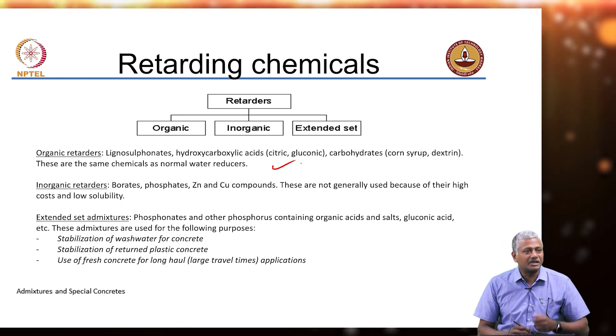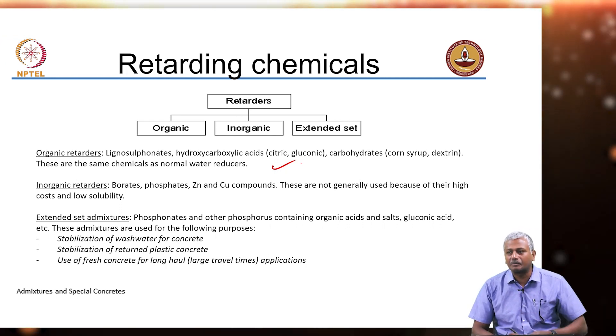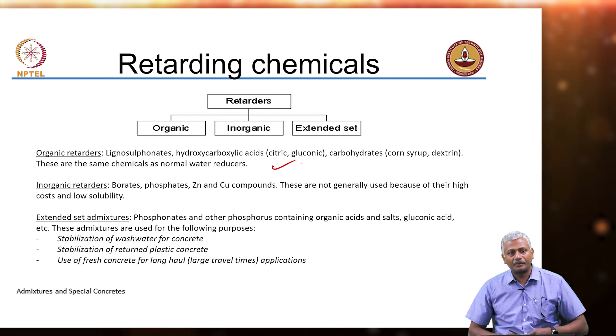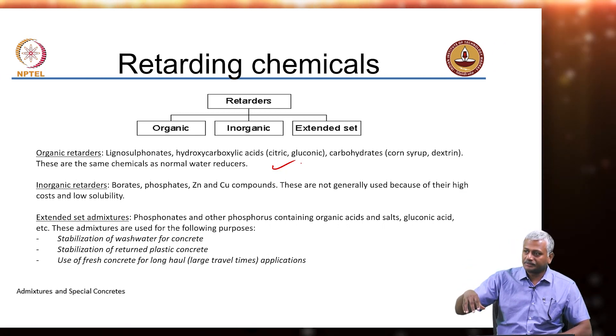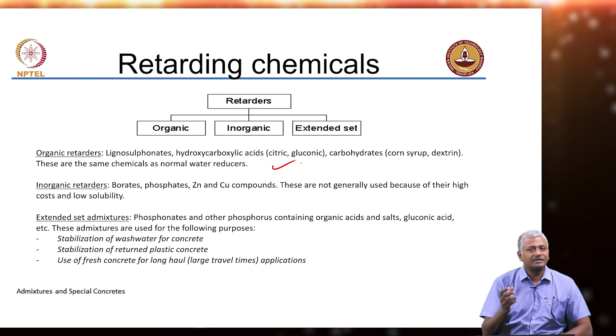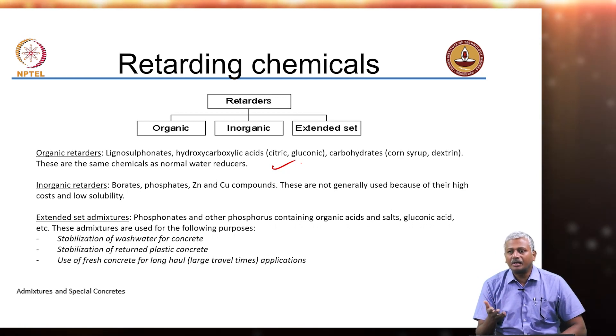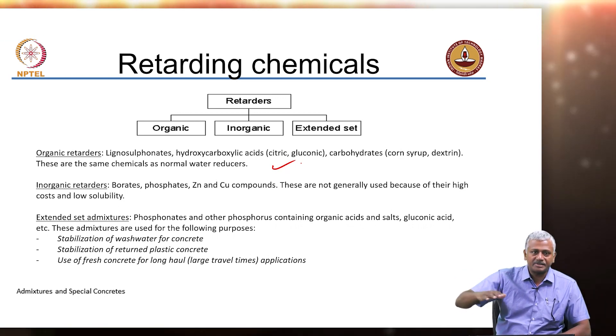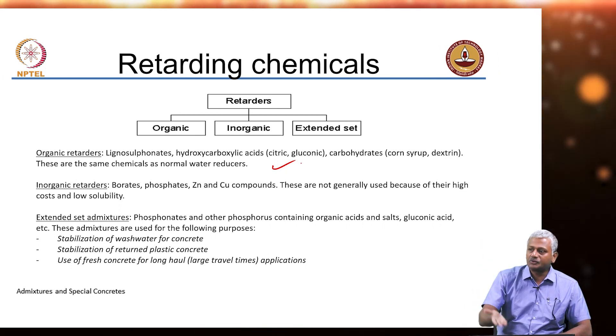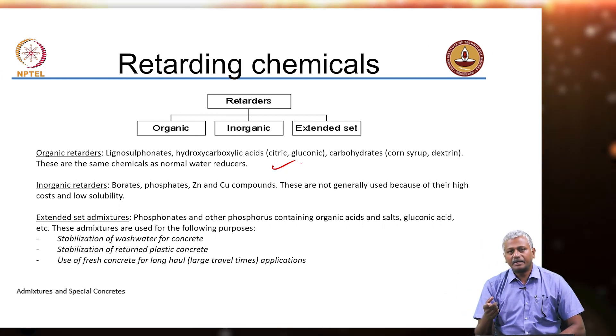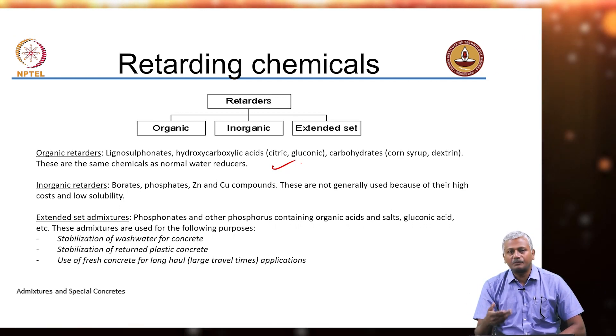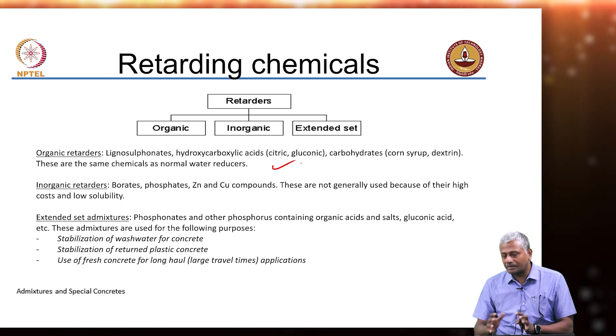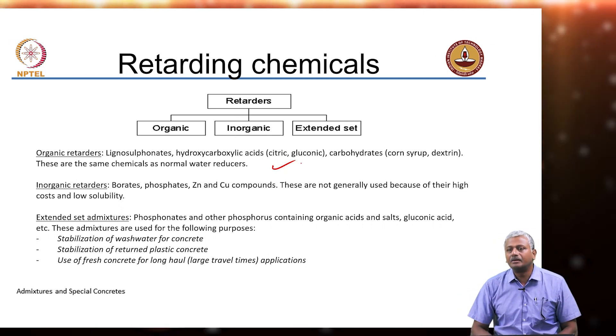In Switzerland while working for Sika, I observed that they collected all their wash water in large plastic drums and added this extended-set admixture into the water. This prevented cement setting completely for several days, allowing cement particles and fine aggregate particles to settle to the bottom. The water remaining on top could then be reused either in new concrete or for washing purposes, while the settled material at the bottom was simply removed and discarded.